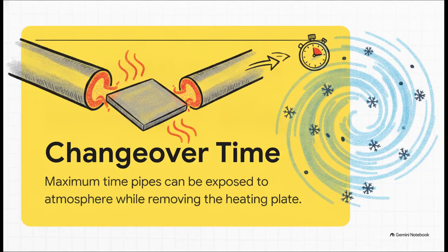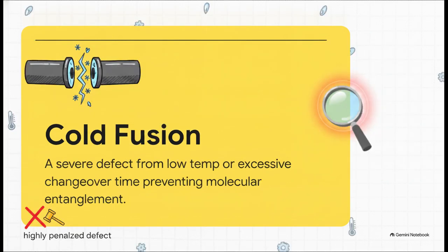Let's zero in on a critical variable in that sequence because it really builds our understanding of failure modes: changeover time. For example, isolate this exact term. Changeover time is the highly critical window during step 3, where atmospheric exposure directly threatens the required heat state of those polymer chains. You have mere seconds to remove the heating plate and bring the pipe ends together. If the ambient temperature is low, or honestly, even if there's just moderate airflow, that exposed molten layer begins to cool immediately. So, the crucial point here is understanding what happens if that changeover time is exceeded.